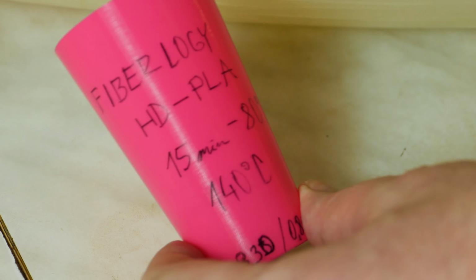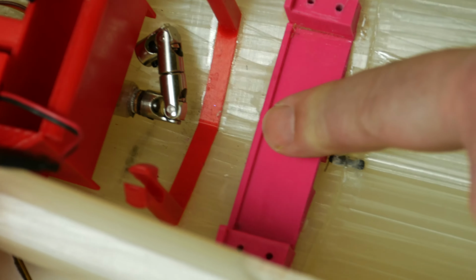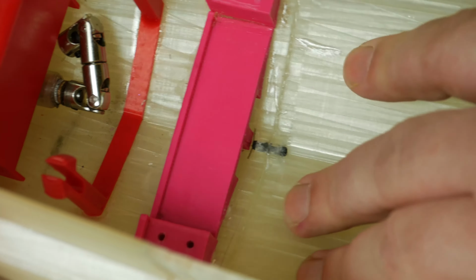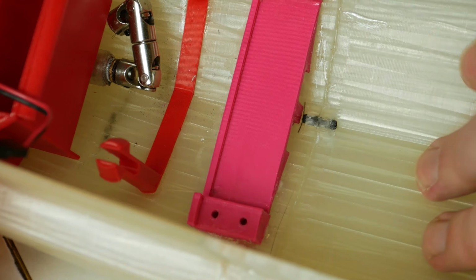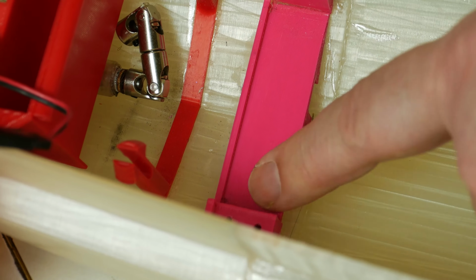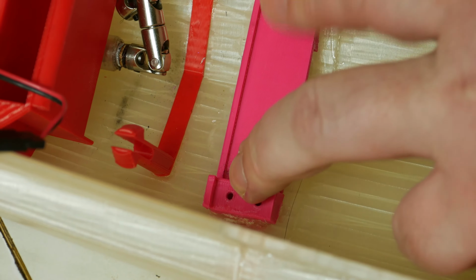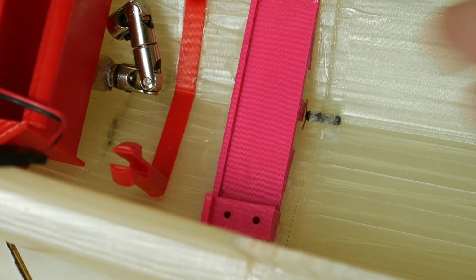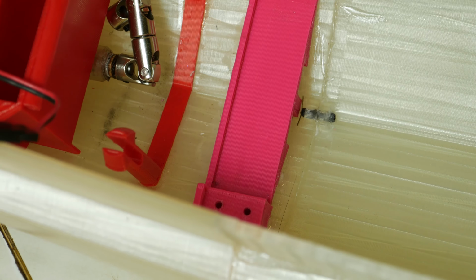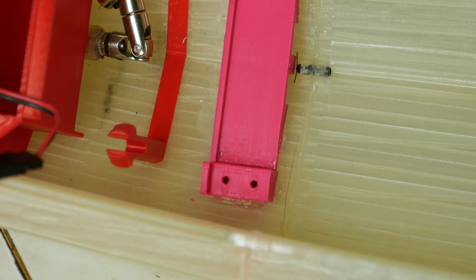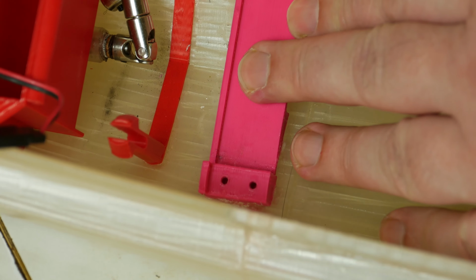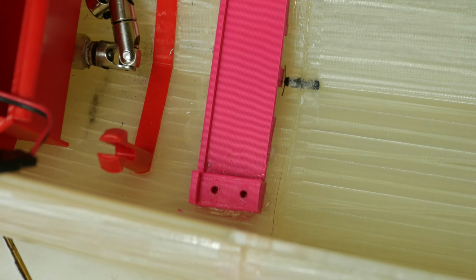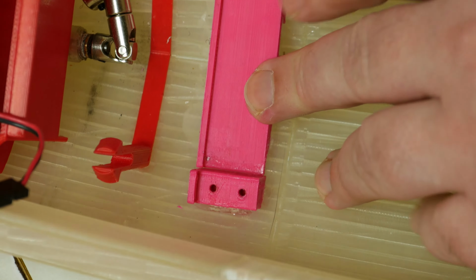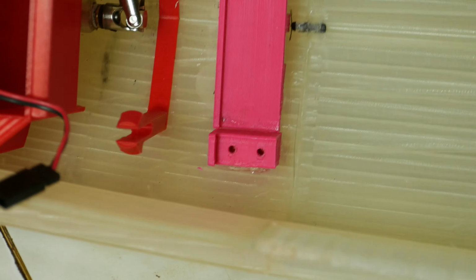and high temperature resistant part. I use this material for a motor mount for my live steam boats. Yes, this white material is just standard cheap PLA, and this pink material is this. And this is the mount for a live steam engine with outside temperature about 110-120 degrees Celsius. And you can see after a few rides of this boat, this part is absolutely without any signs of deformation by high temperature.